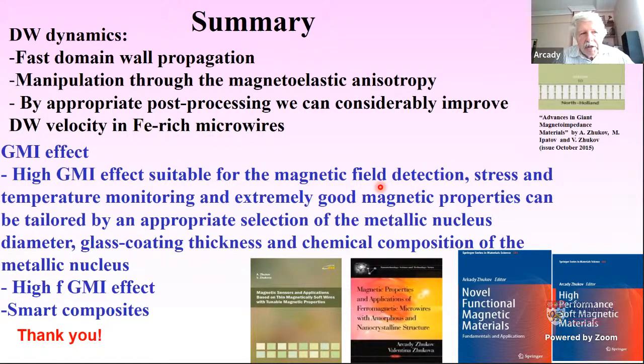In any case, I didn't show it, but in the case of iron-based materials, we can get so-called nanocrystalline materials. The problem is again the magnetic properties. For electrical contacts, for example for magnetic field measurements, we should pay much more attention. But they sometimes present comparable magnetic properties and also good magnetic fields, for example Finemet materials. But these are not iron cobalt-rich materials. Usually, iron cobalt-rich crystalline materials present higher magnetic anisotropy, and therefore they are relatively magnetically hard.